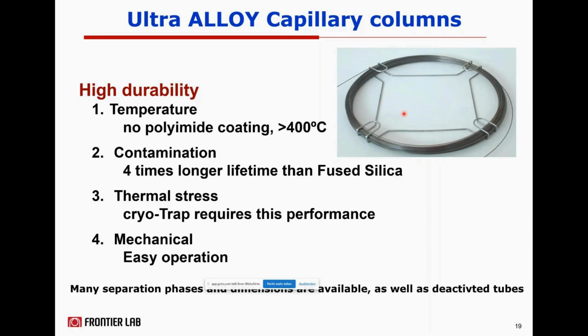capillary columns. So maybe you don't know, but the Ultra ALLOY column was actually the first product launched back in 1991 by Frontier Lab. And the big advantage of the metal column is the excellent durability. We do not have any polyimide coating, so the temperature stability is very high, and we can run GC oven programs above 400 degrees Celsius. It's less sensitive to contamination, so we have basically 4 times longer lifetime than fused silica columns. So it's very resistant to thermal stress.